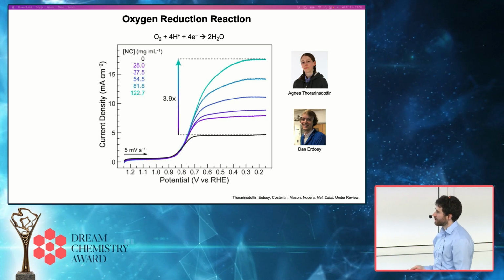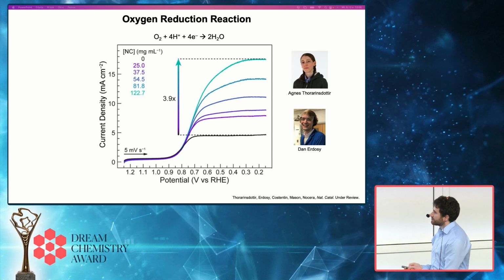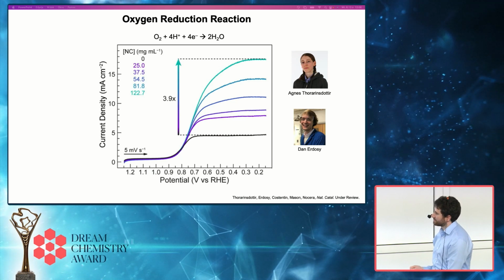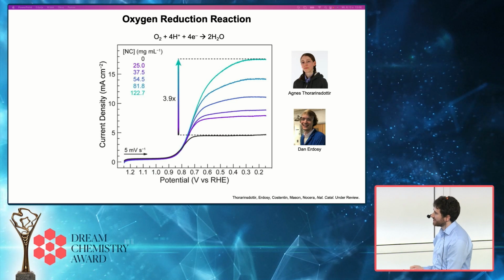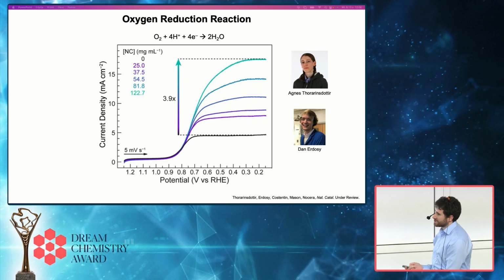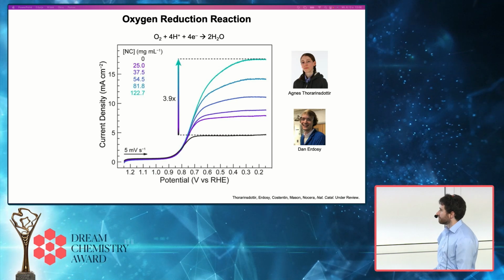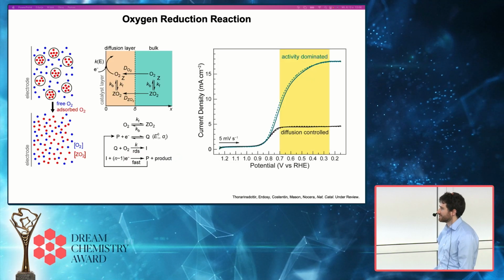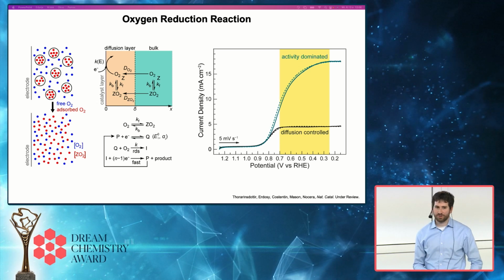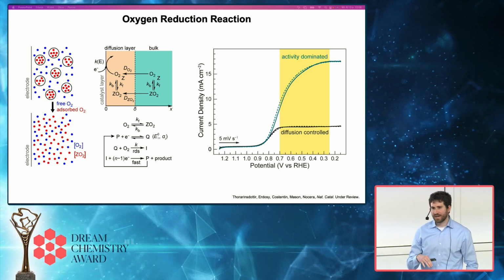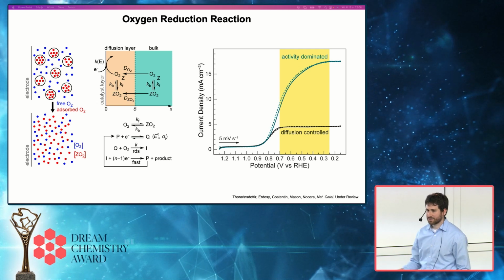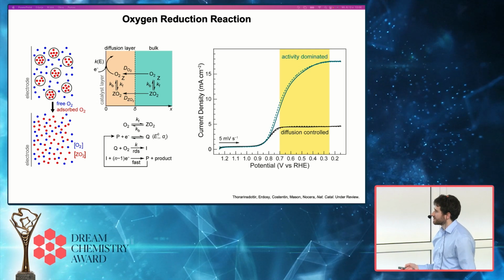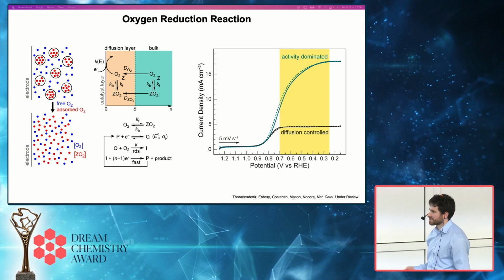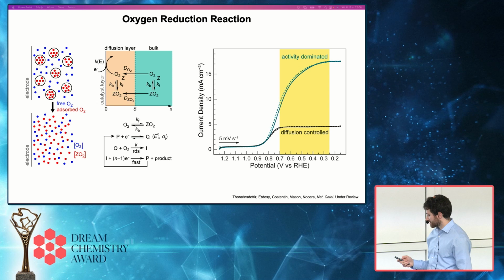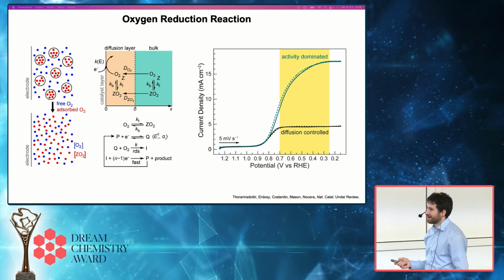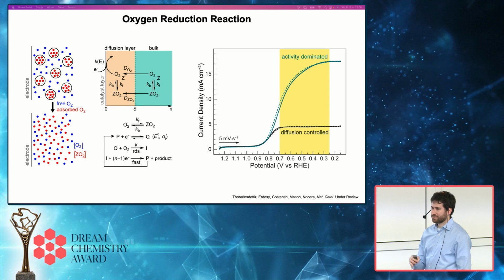The other thing we were really excited about was that as we are able to achieve these higher current densities, we see a shift to lower potentials, or higher overpotentials, in where we actually reach this plateau current density. And through some modeling efforts, what we were able to understand is that we are actually approaching a region where we're limited by the intrinsic performance of the catalyst rather than limited by mass transport of oxygen through water. So under normal conditions, we're really just limited in terms of the current density we can achieve by oxygen solubility and mass transport of oxygen. But under these high oxygen electrolyte conditions, we're more limited by catalyst performance.